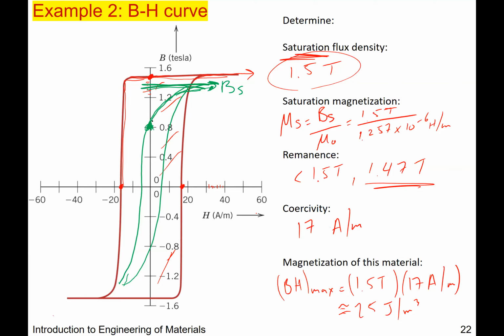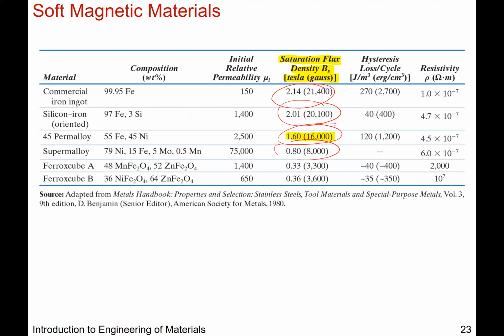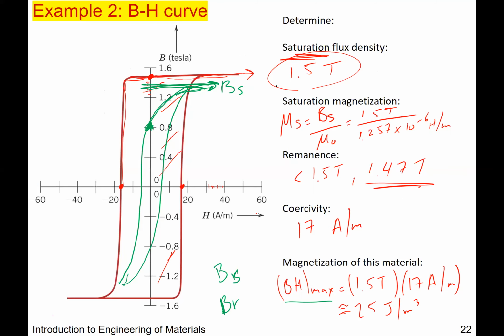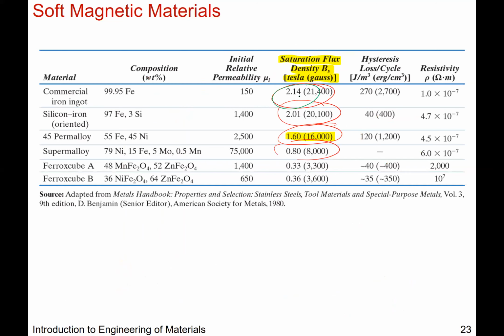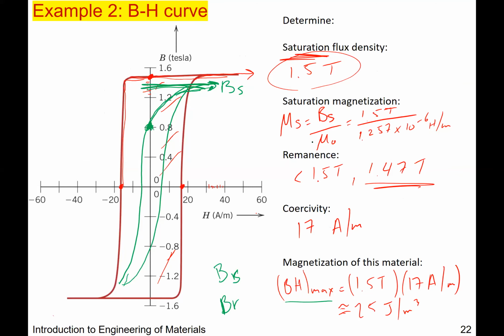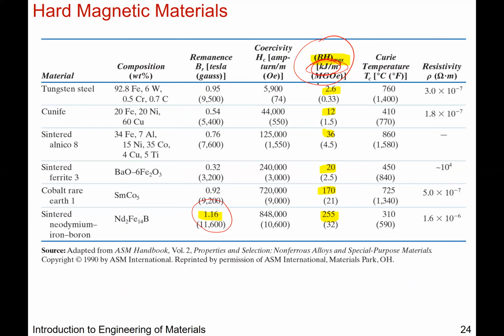So another question that popped up is, why is it a soft material again? Well, we looked at 3 values. We looked at the saturation magnetization, the remnants, and then BH max. And so we had two conflicting results. If we looked at the saturation flux density, it rivals that of soft materials. So 2.14 to 1.6, that's on the order of 1.5. They're on the same order. But if we look at the remnants, it's not so clear, because these values are somewhat comparable. They're on the same order of magnitude, 1.16. So which one is it?